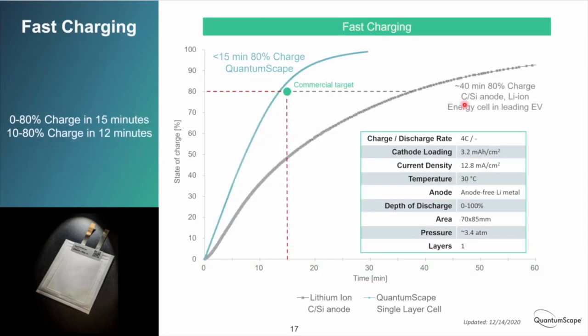So then fast charge is another really key requirement, we think. So how do our cells do in fast charge? This, in blue here, is data that we collected on cells in our lab showing fast charge capability. The y-axis is the state of charge over time on the x-axis. So we did here a 4C charge rate, and you can see the cell charging up quite quickly. It beats this target we have set for ourselves of 80% in 15 minutes.